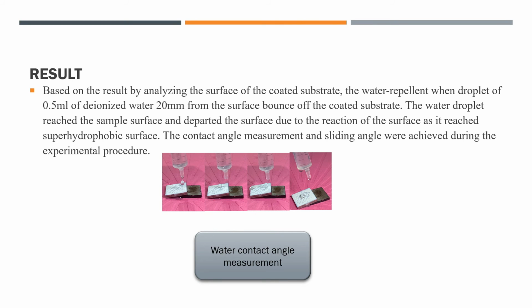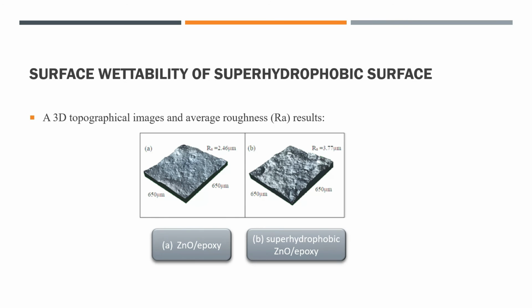Based on the result, by analyzing the surface of the coated substrate for water repellency, one droplet of 0.5 ml of deionized water from 20 mm above the surface bounced off the coated substrate. The water droplet reached the sample surface and departed the surface due to the nature of the surface, as it was a superhydrophobic surface. The contact angle measurement and sliding angle were obtained during the experimental procedure. The water droplets bounce off the superhydrophobic surface.